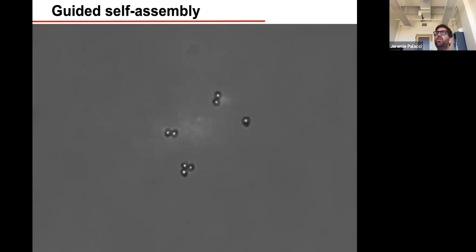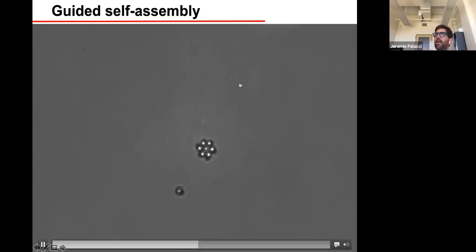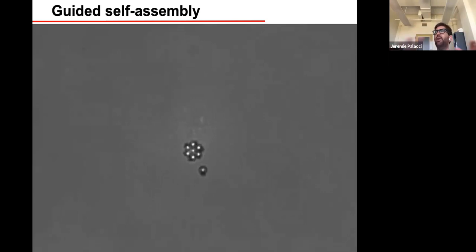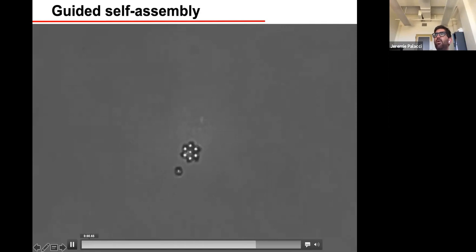And that's really an essential feature. If you want to build a complex architecture, you have to have the right to fail and disassemble. So it disassembles a bunch of times, but eventually it's going to form this microgear. Now that the microgear is formed, you can turn off the light gradient. You just need to keep some light, obviously, otherwise the system is in equilibrium and everything breaks down. But now the light is uniform and you can form those self-spinning gears. And they can stay stable for up to an hour.